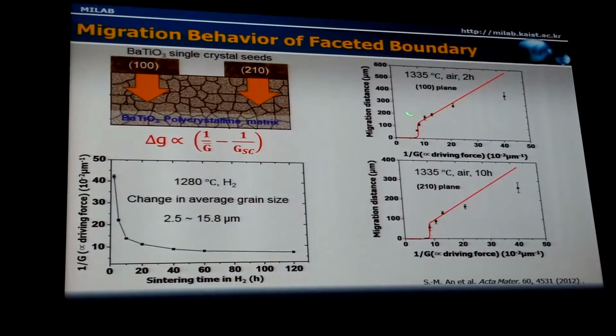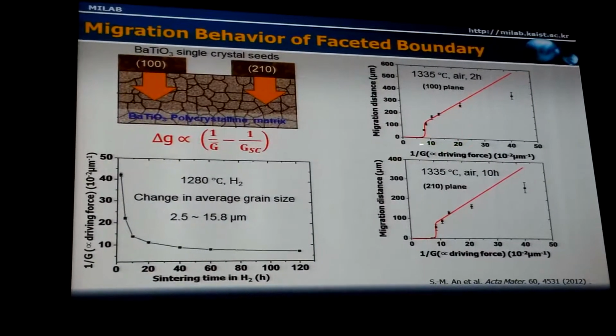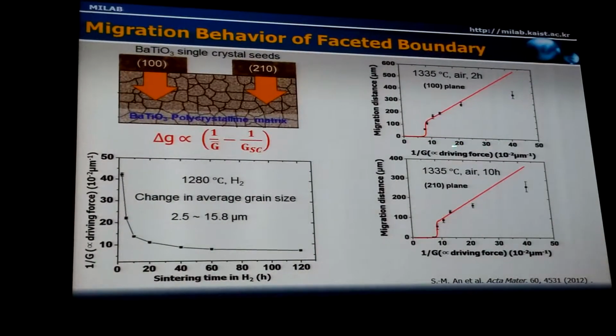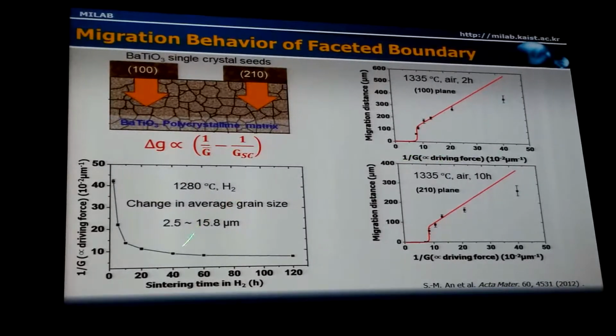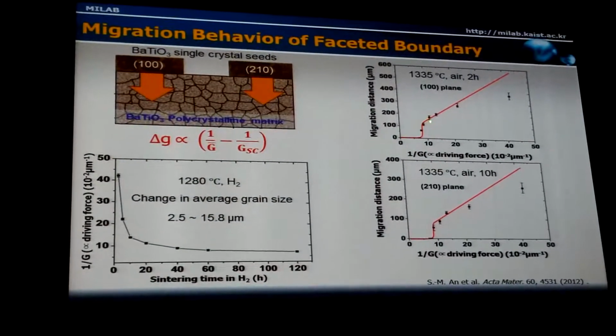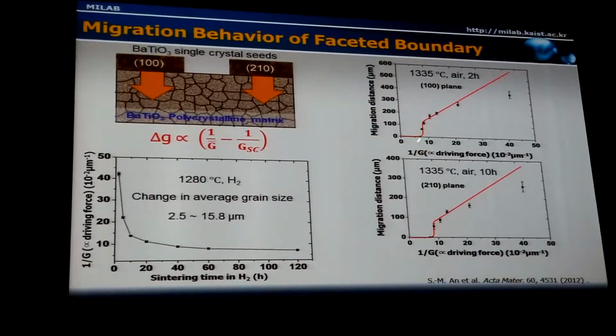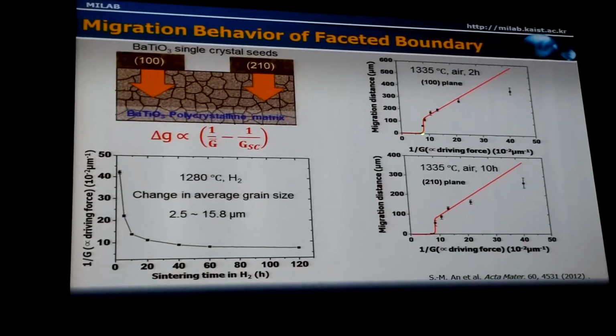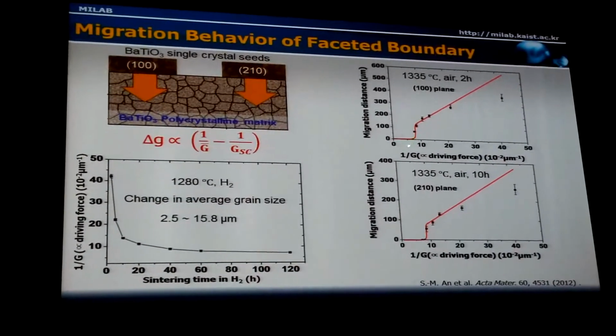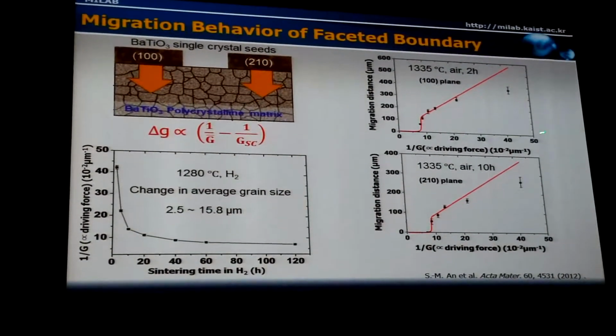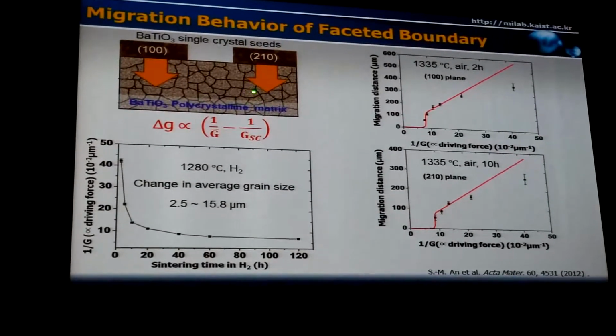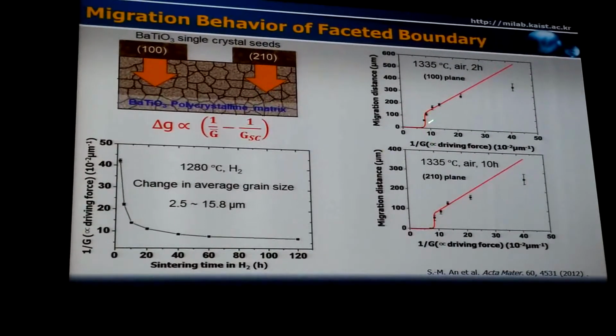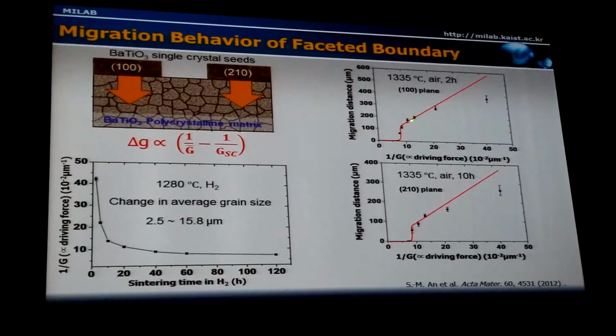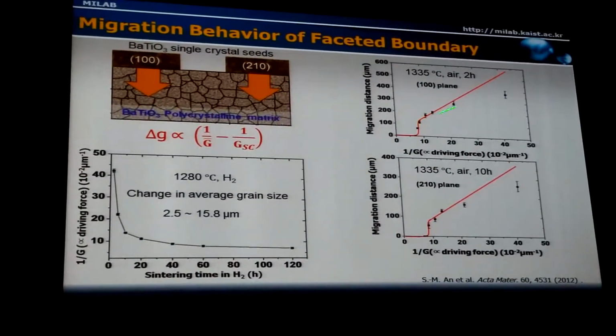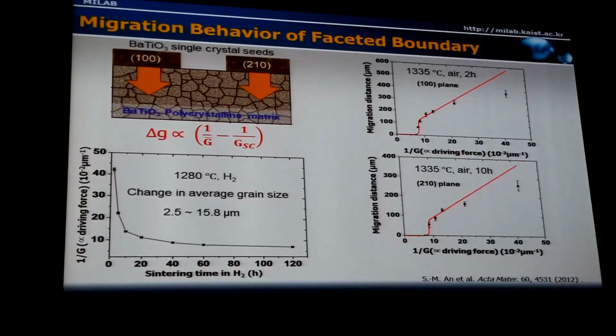Well, this is a result of the migration distance as a function of the driving force, which is inversely proportional to the average grain size of the polycrystal. As you can see here, apparently there's no migration when the driving force is small, but as the driving force increases, that means the average grain size decreases in the polycrystal, then migration distance increases more or less linearly with the driving force.